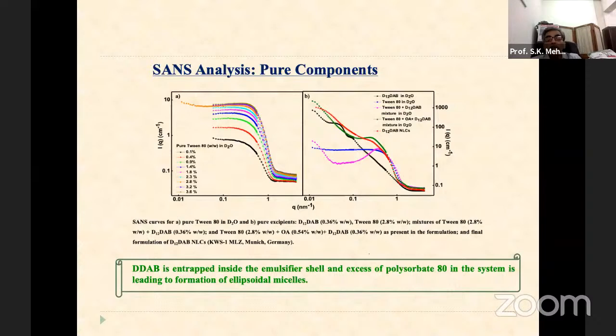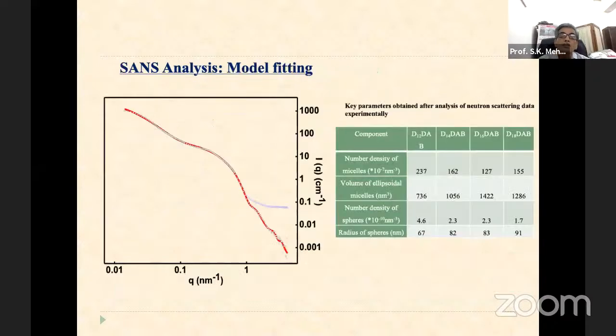And finally, it was found that this DDAB is trapped inside the emulsifier shell. This was proved by scattering analysis. And the excess of Tween 80, that's polysorbate, in the system is leading to the formation of ellipsoidal micelles. So these ellipsoidal micelles, which we could find that they are formed, cannot be found from other techniques like TEM, SEM also, they don't tell us clearly about this. So the scattering techniques are very useful. They can tell us about the exact shape of the systems.